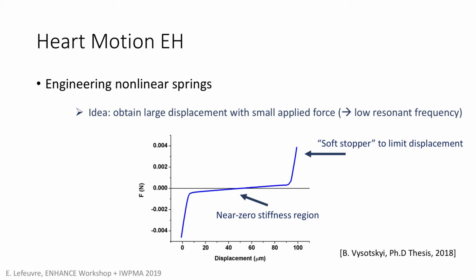And if you remember the acceleration spectrum I showed before, we need a small resonance frequency in the range of 20 to 30 hertz if we want to have a resonant effect in the system. And of course, if we have a resonant effect, we have an amplification of the energy conversion, and it's beneficial for the application. And the problem with the system is that we have a limited space in the capsule, and the system is in silicon, so we don't want to have shocks.